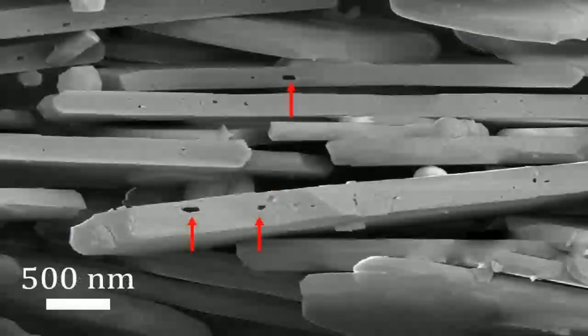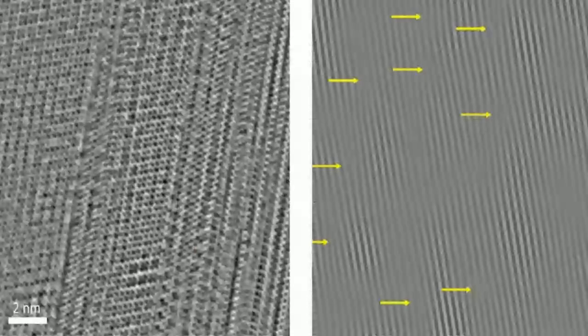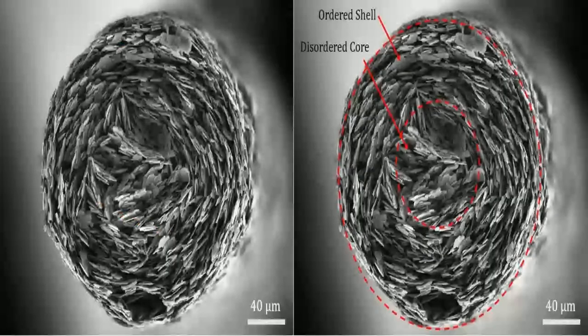So ceramic fibers in a plastic matrix? Sort of. They printed a skeleton of just the aligned carbon fibers first, then infiltrated that fragile skeleton with a polymer, like epoxy resin. How did that approach work out? What were the results? Well, they definitely ran into challenges, like getting bubbles in the initial fiber paste during mixing and printing, and the fact that the printed fiber structure, after burning out the paste binder but before adding the polymer, was incredibly fragile and hard to handle.